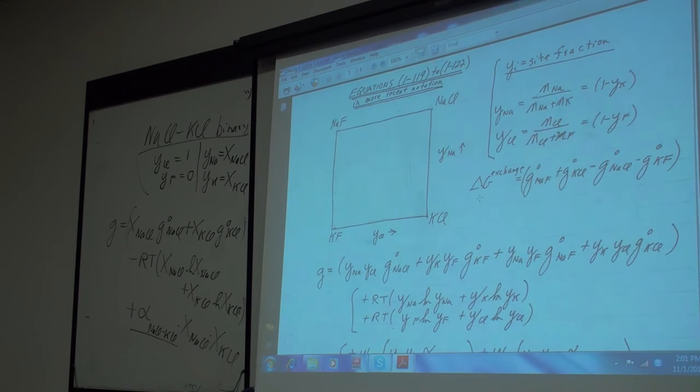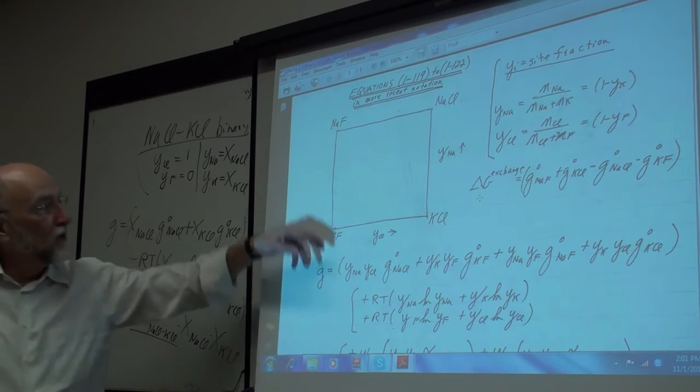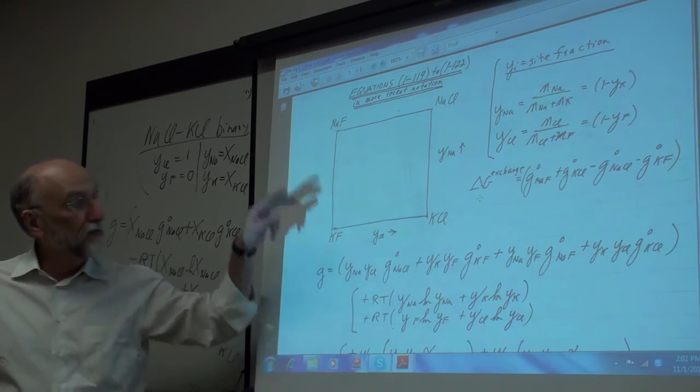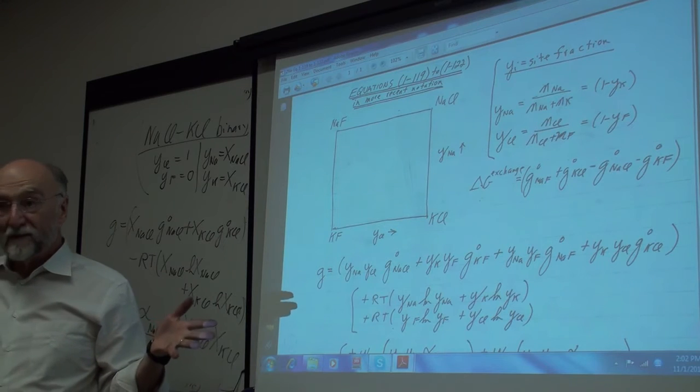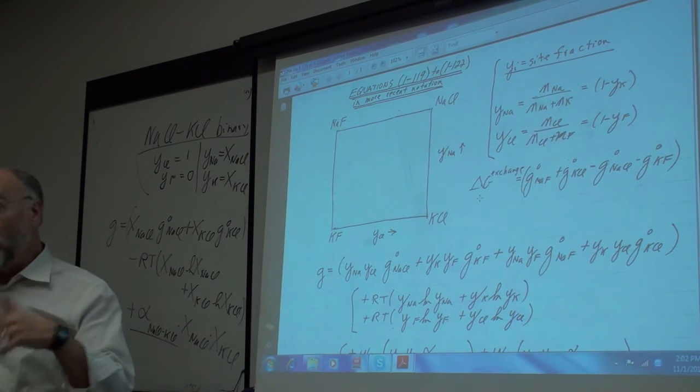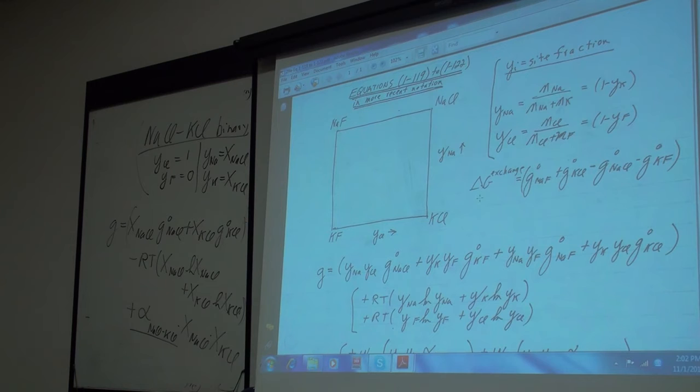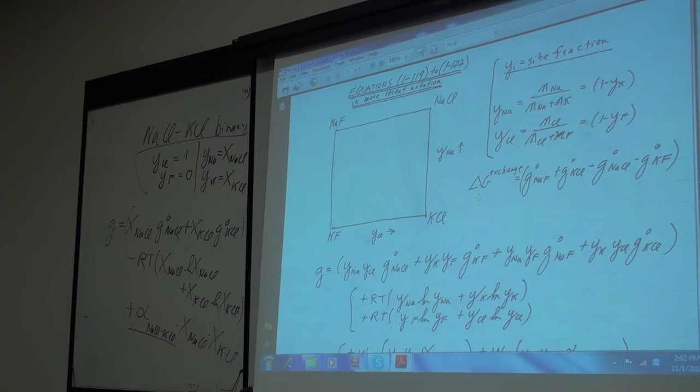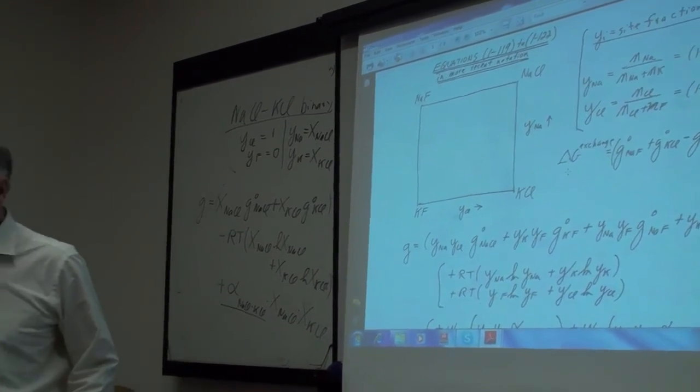And of course, the slags, the molten oxides that you're using, are treated like molten salts, and this is exactly what we're doing. In the molten oxides, the one sublattice is occupied by oxygen. So you're really treating, say, CaO-MgO as if you're forgetting the oxygen, and you're just treating the calcium and magnesium mixing on the sublattice.